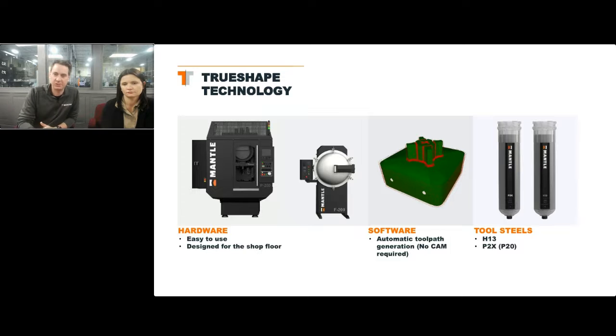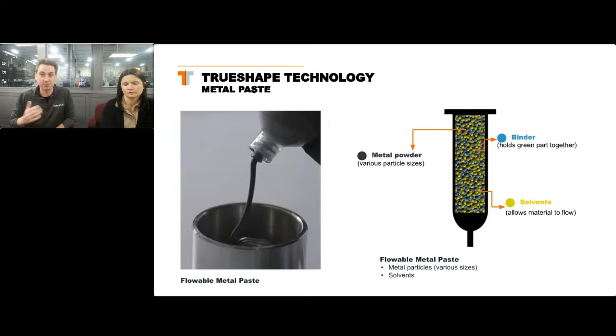What makes our process so unique is that we're not starting with a metal powder or a filament, we're actually starting with a paste. And that's what we're printing. This paste has the consistency of about a toothpaste. It's relatively viscous. What that actually is, is metal powders mixed with binder and some solvent to allow it to flow.